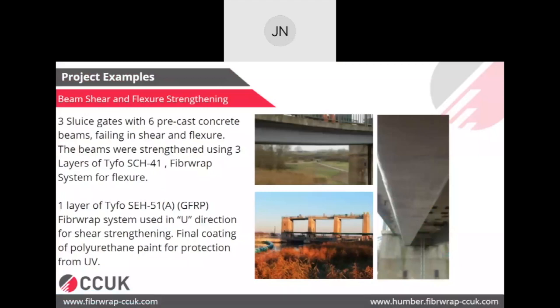Similarly, this is another example. This is a beam strengthening now, and it's from a sluice gate structure, which is more like a bridge type of structure. So in this case, you can see there are three gates supported by two of these precast concrete beams on each gate. There were major stress cracking in these beams. They were not able to lift these gates up and channelize the water. And that's why they wanted to do strengthening of these beams, because this was part of a major flood relief work and they needed these sluice gates to operate as soon as possible.